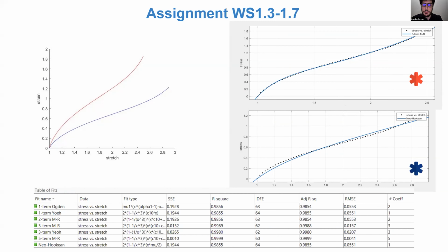We imagined testing the system in the unjammed and jammed state in order to evaluate its mechanical properties when it exhibits the two different stiffness values. So, to model the system stretching in relation to the forces applied, we used the hyperelastic models proposed during the first workshop that we attended, and we fitted the experimental curves reported here. As you can see, the model that best fits the first elastomer is the three-term Yeoh, whereas the first-term Ogden and the Neo-Hookean have proved to be the best fit for the second elastomer, as you can see from the fitting parameters, like root mean square error and others that are shown at the bottom of the slide.